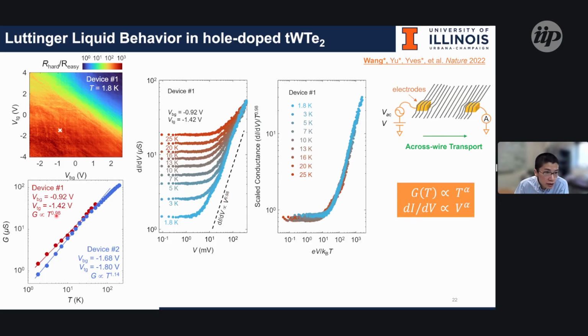You can also see that the power law for the device, on the temperature power law, is around 1, and we also get a power law around 1 here for the bias as well. So it follows very well with the external bias. This mimics one-dimensional Luttinger liquid behavior, but we observe such behavior in a two-dimensional situation, giving you a single alpha and power law conductance along the hard direction.